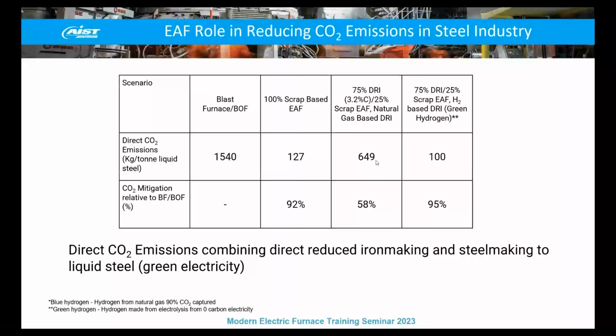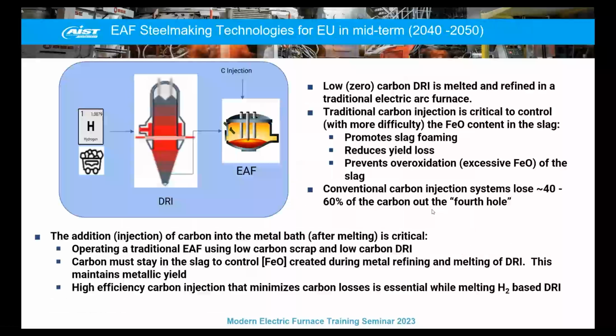75% DRI, this is natural gas based. So you still have some CO2 emissions, but significantly less — say half, I know it's 58%, but half of the blast furnace. And then using green hydrogen, you still have some level of CO2 emissions, but significantly less than that of the blast furnace.